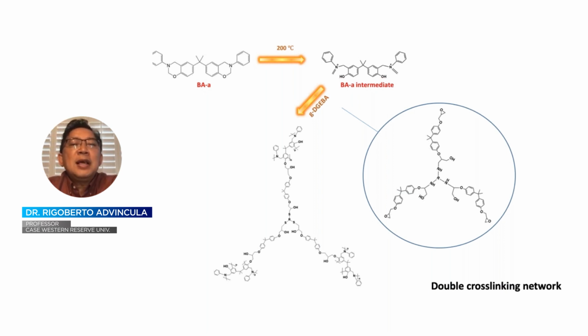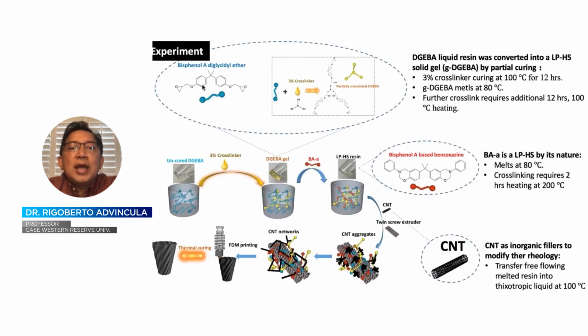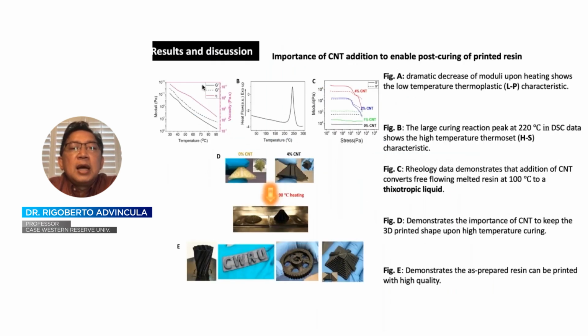When you mix the benzoxazine and epoxy, they cross-link as shown in this diagram, where the cross-linker can be designed based on the added intermediates or the presence of your amine groups as well. So amine with regards to epoxy, but you have benzoxazine activated by temperature or simple heating to cross-link as well. So using these two cross-linking methods, we were able to 3D print them and produce different shapes as well. So for example, as shown here, this rheologically appropriate materials, in addition to the CNT or carbon nanotube, can be made into hard objects as shown here in